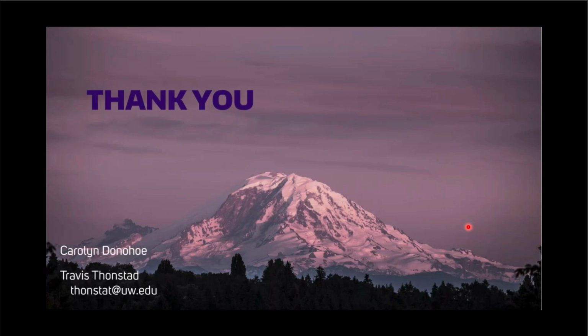Okay, here's one that came in during the webinar, very early on. It said, with challenges listed with temperature dependence, do you have data on the high temperature limit range? Yeah, I think that's a very important question. For us, we were certainly looking at service temperatures, considering things lower than 120, 110, somewhere in that range. We did test one point out at 145 Fahrenheit, and you saw that was a significant reduction in strength there.